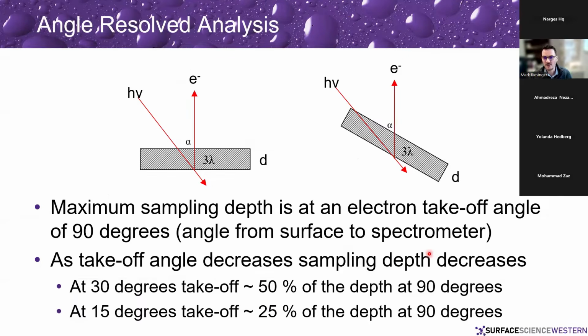Another way that you can change the depth of analysis is by changing the takeoff angle of your sample or the tilt of your sample. So if you have a normal takeoff angle, that's your maximum depth. Your spectrometer would be up here, and photoelectrons are coming straight out here. If you tilt your sample, you're now changing that 3 lambda to a shallower depth as you tilt that sample. At about 30 degrees takeoff angle, you get about 50% of the depth at 90 degrees. At 15 degrees takeoff angle, you get about 25% of the depth at 90 degrees.